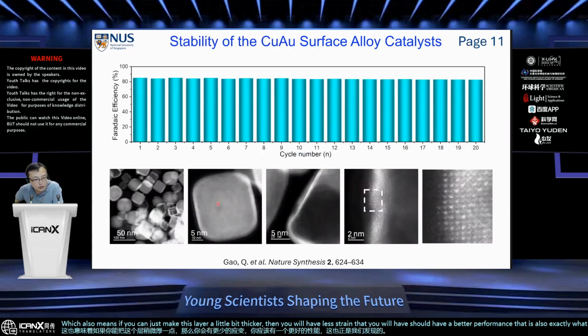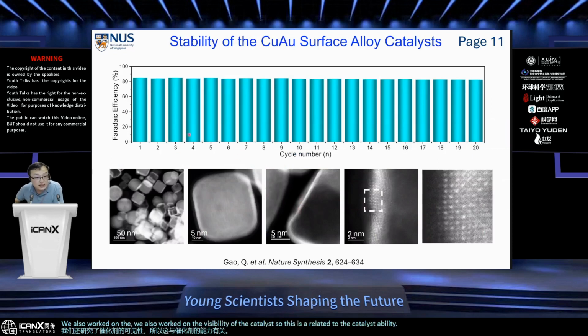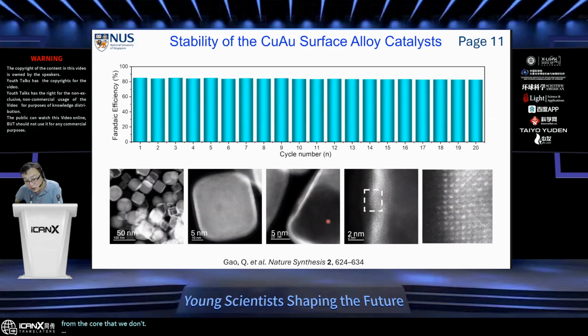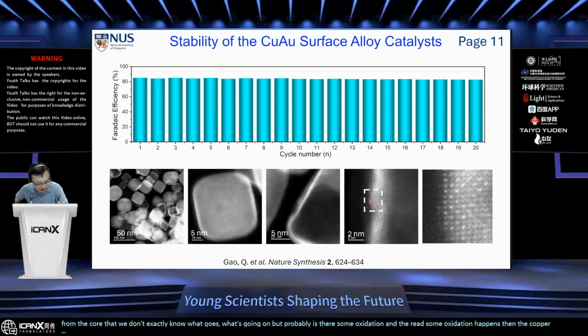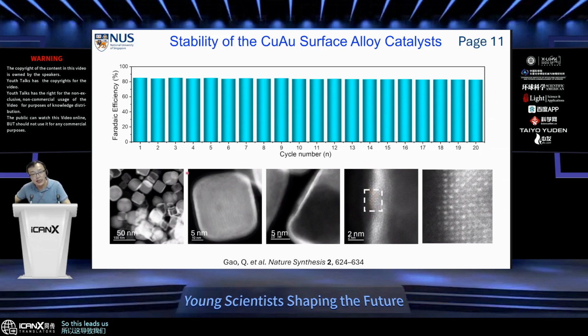We also worked on the reusability of the catalyst. So this is related to the catalyst stability, right? And you can see that by 20 cycles of the reaction, it works pretty stable. It works very well. If you look at the catalyst after 20 cycles, you can see that the intermetallic layers are still on the top, even though some of the copper metals get leached out from the core. We don't exactly know what's going on, but probably there is some oxidation, and then the copper cations may get dissolved into the electrolyte, but the intermetallic still remains on the surface.